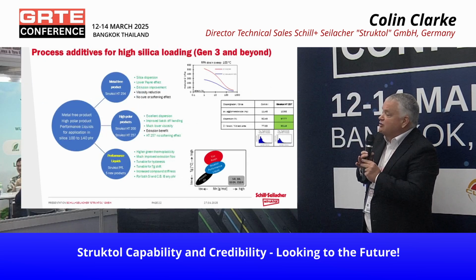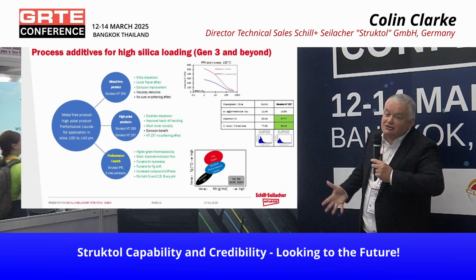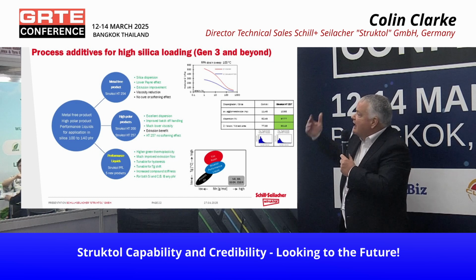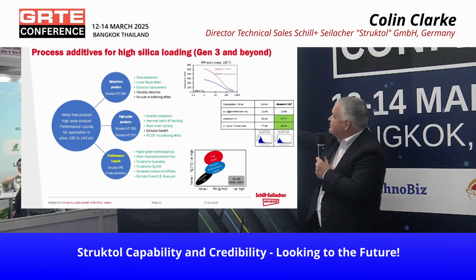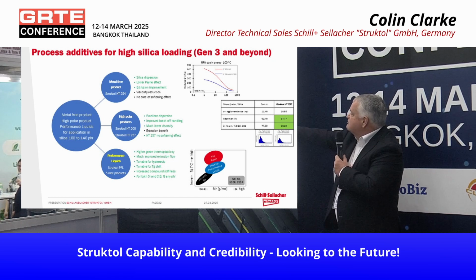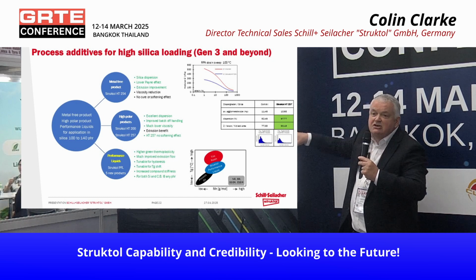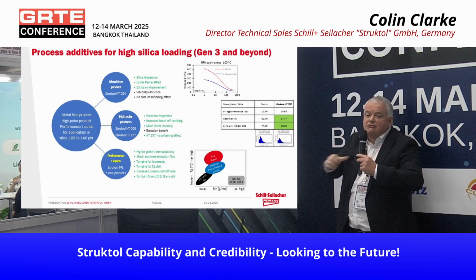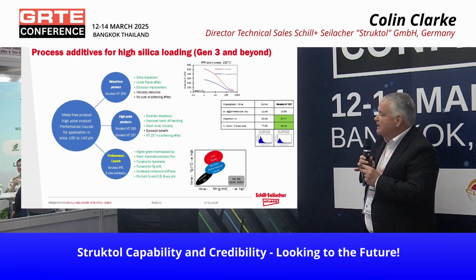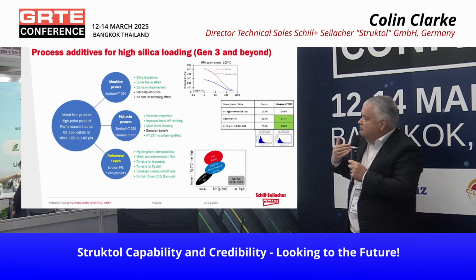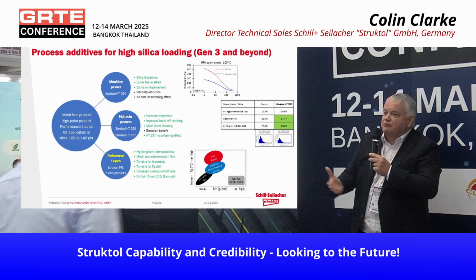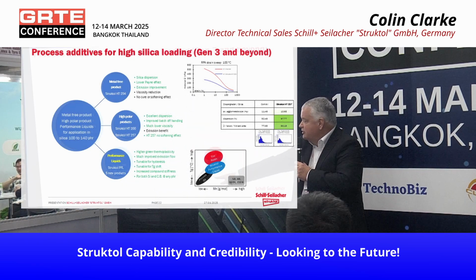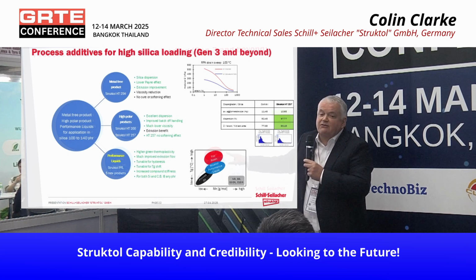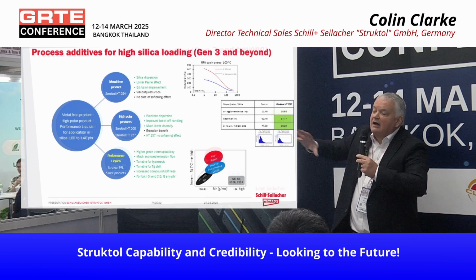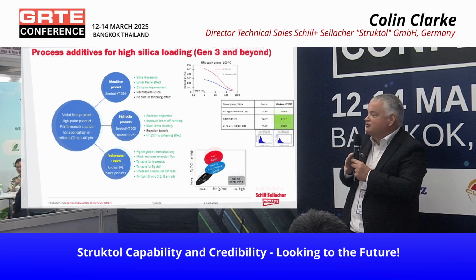But that's not the end of the story, because the tyre makers push the silica level even higher. And so, of course, new challenges mean new additives. And now we have additives that really target to improve the silica dispersion. We can see dispersion from 77% up to 90% with additives. So really targeting to strongly interact with the silica and maximize the filler dispersion. And finally then really, if you like, functionalized liquids, so reactive products that sit somewhere between the process oil that you use and the polymer, or the resin if you like. We can position then reactive liquids that can strongly interact with the polymer and the silica to maximize both the processing and the properties of the tire.